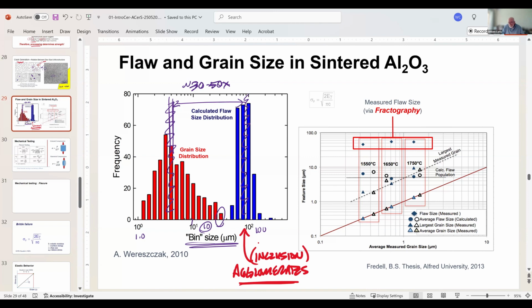But this data is really telling, and it's also interesting because at the same time that Andy was generating this data, we were generating our own data, and this was one of my thesis students from 2013. There's a lot going on in this slide, but here's your average measured grain size for a series of samples. So this is average grain size, 0.1 to 10 out here. And there are different temperatures. There were two bodies evaluated, and these are three different temperatures: 1550, 1650, and 1750.